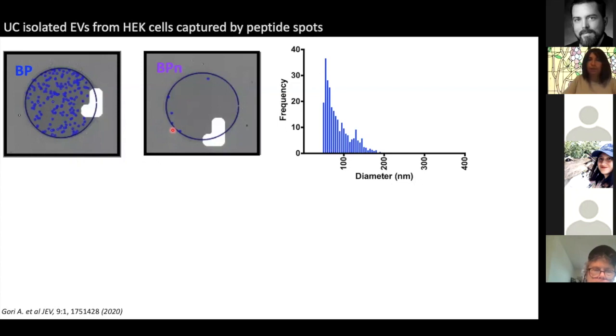And this is the size distribution of captured vesicles provided by the NanoView instrument. As soon as we did these experiments, we noticed a preferential binding for the small vesicles, so from 50 to 150 nanometers in size. However, we will go back to this data at the end of my presentation.